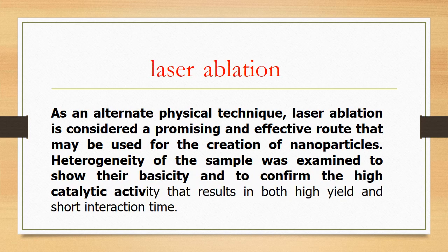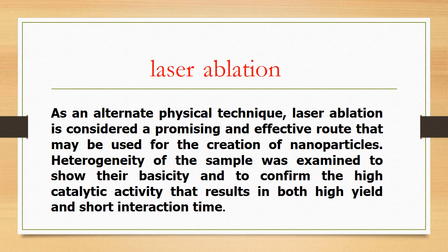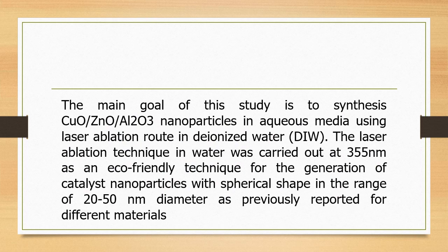Now we transfer to another slide. The main goal of my study is the synthesis of copper oxide, zinc oxide and aluminum oxide nanoparticles in aqueous media using the laser ablation route in deionized water. The laser ablation technique was carried out at 355 nanometer.